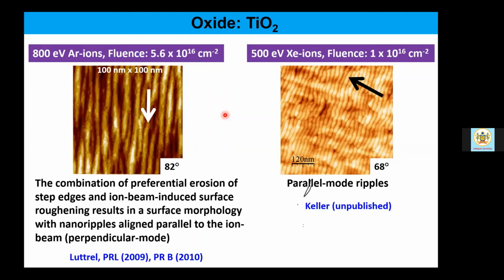And the combination of preferential erosion of step edges and ion beam induced surface roughening can once again be attributed as resulting in the surface morphology with nanoscale ripples aligned parallel to the ion beam. That's the parallel mode ripple. But here it was at 68 degree, as expected.